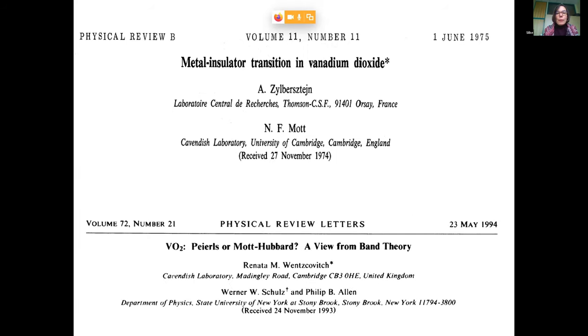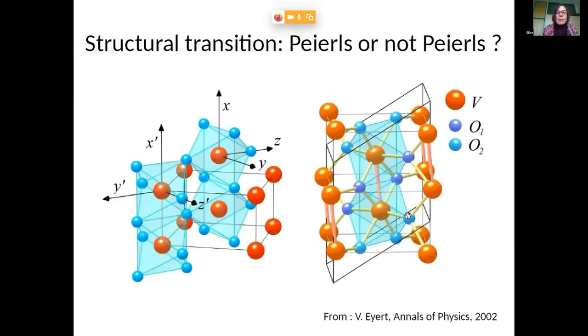In 1994, there came strong counter arguments against that by a collaboration of Wentzcovitch, Schulz, and Allen, who did DFT calculations and, in particular, focusing on structural properties, found out that the structural properties were not so badly described in density functional theory, and also with the argument that one might just need a little bit to split off the lowest band, one might even have a Kohn-Sham band structure that could become insulating at the DFT level. Okay, what are we talking about? Structural effects, more band-like than correlated.